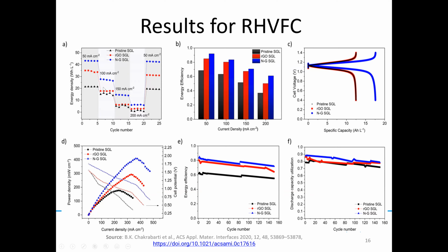Usually a vanadium flow battery at around 80 to 120 milliamp per centimeter squared has an energy density around 25 watt-hour per liter. With the nitrogen doped system, we are getting slightly higher, and even at higher current densities, the vanadium system goes lower. So maybe around here somewhere, we are getting higher energy densities for the nitrogen doped graphene. Another key performance indicator for flow batteries is energy efficiency. At different current densities, we can again show that energy efficiency is better for the nitrogen doped graphene deposited onto the carbon paper by means of electrophoretic deposition.